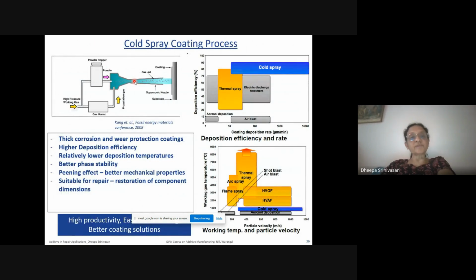Then, as I mentioned to you, it's a convergent diverging nozzle. Powder particles go and form a coated layer on the substrate that you can see here, without having any of the ill effects of conventional thermal spray process in terms of poor deposition efficiency, and not being very effective for restoration of components. There are so many advantages. Basically, it is relatively cold spray, and you can even make coatings, or you can make material as thick as even 25 millimeters, 20 millimeters, 15 millimeters. All it has to do is it has to be a metal which is undergoing plastic deformation in order to be able to spray on this.